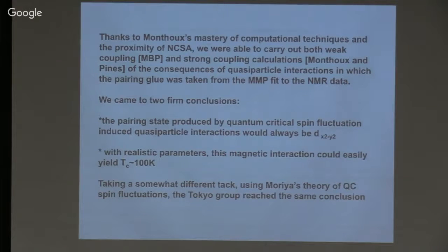And a graduate student, who's a very bright kid, I had no idea that he was computationally literate and in fact computationally imaginative. And he was able to use the high-speed computers then present in Urbana to show that when you allowed for the frequency dependence of that interaction, you could really get a high-temperature superconductor. It increased by a factor of 10 the earlier estimates of how effective the spin fluctuation interaction could be if you just kind of averaged over everything. If you allow for the frequency dependence, TC goes up about a factor of 10. So our conclusion, also reached by the Japanese, was the pairing state would always be dx squared minus y squared, and you could really get high TC.